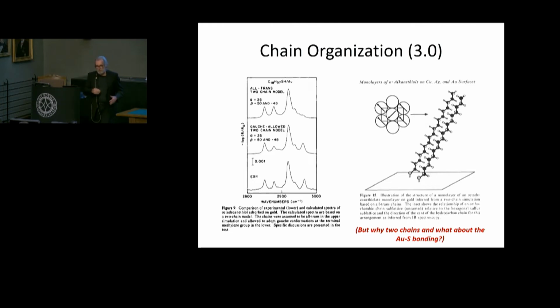And that's where I would have passed around in the audience. This is precious, okay? You'll not be able to see this. This is actually a spectrum that was plotted in 1988, okay? That was measured looking at a hexadecanethiol monolayer on gold (111) single crystal, looking at the methylene bending vibration at 100 Kelvin, right? So this was actually the most complicated IR experiment that we did back in that day.